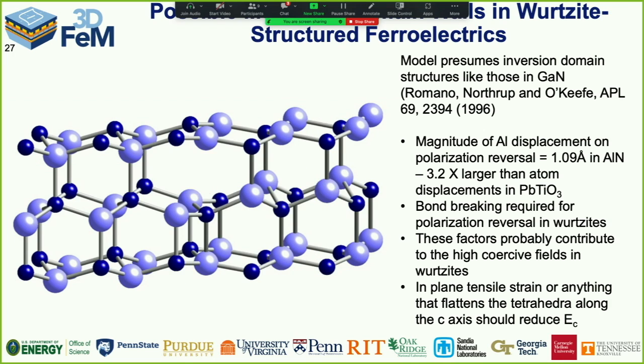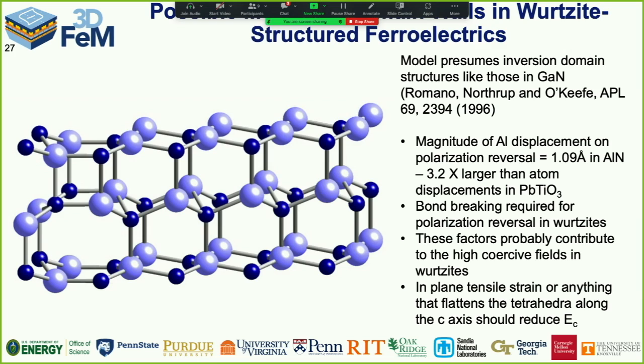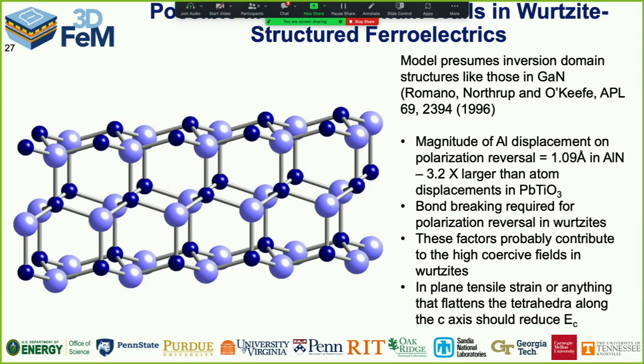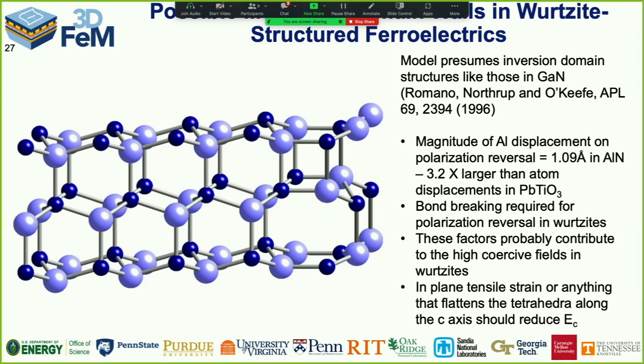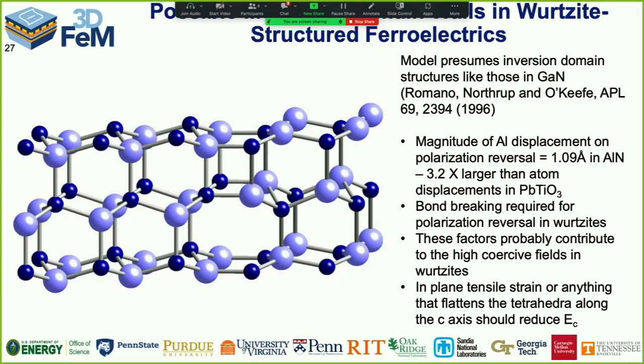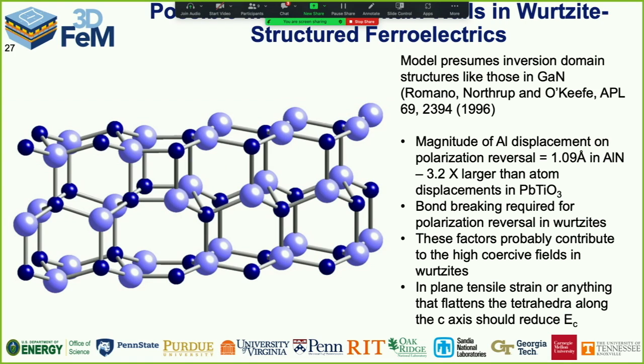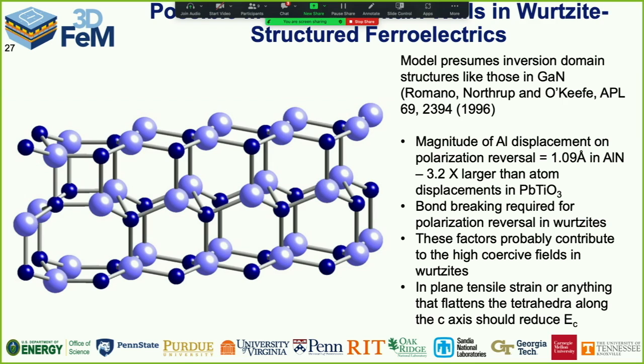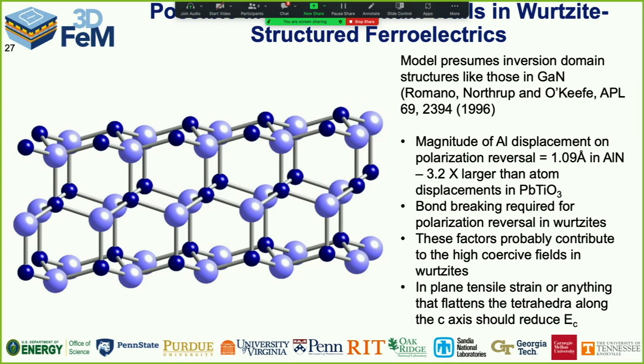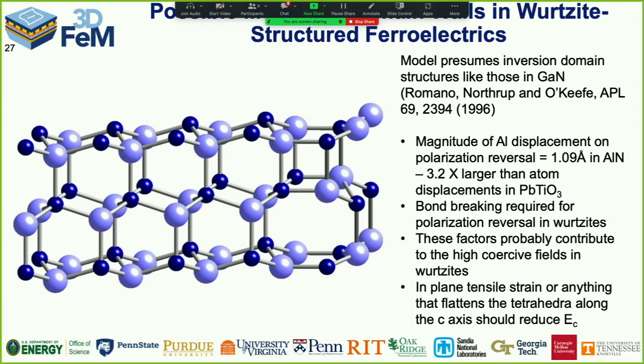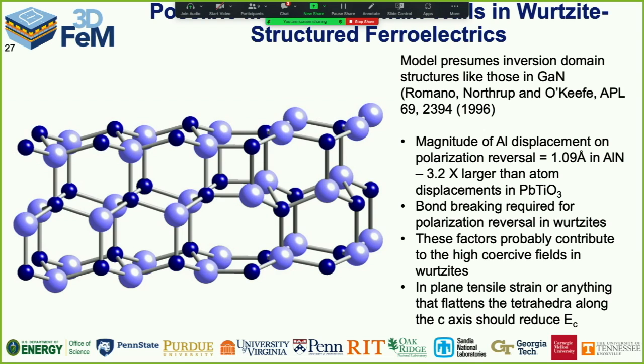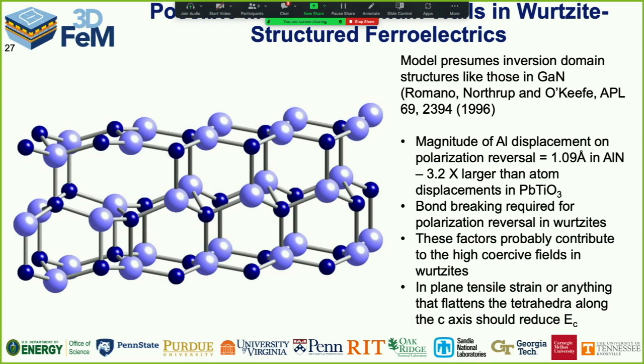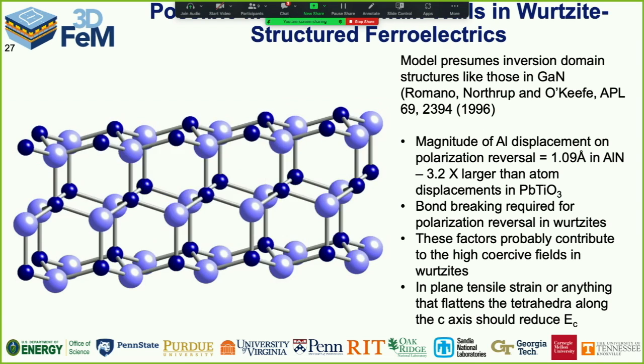The animation that you're seeing here is one that I took. This is a hypothesis. This is not proven. It actually turns out to be brutally hard to prove this. But we took real known anti-phase boundaries in gallium nitride, which have exactly defects of this type, and we speculate that if I can move that defect back and forth, I should be able to run polarization reversal.